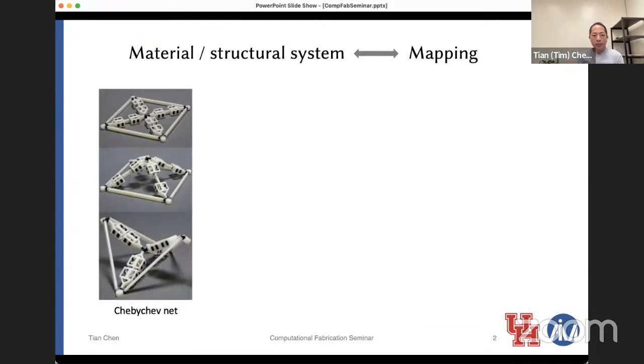With many bistable units tiled next to each other, each unit cell can snap without the neighboring snapping. So these are, in fact, all the intermediate states. Of course, we didn't design for them, but they are stable states that we can achieve. But in this project, we explicitly designed for a planar structure to transform to 2 different global structures, 3D structures that have 1 set or 2 sets of the bistable units triggered. So the diagonal length goes from length 1 to length 2 or 3, and then globally, of course, they go into 2 different structures. This is just a picture of the exact same unit cell that goes into the 2 shapes below. For the auxetic sheets, that's something we don't know how to do yet. That's something we're looking into.